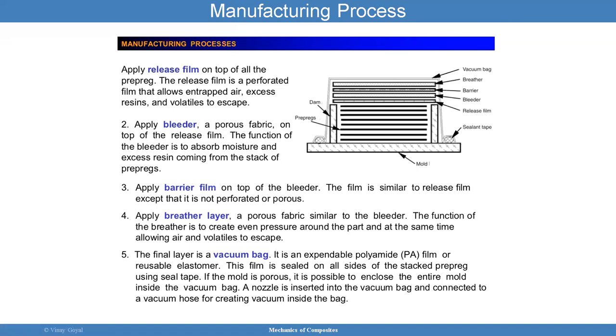We apply bleeder, which is a porous fabric, on top of the release film. And that lets you absorb the moisture and excess resin. Covered that already. Apply a barrier film on top of the bleeder. The film is similar to a release film, except that it is not perforated or porous. And then we apply a breather layer. And the breather layer typically allows you to apply even pressure, like I said before, around the part, and at the same time allows air and volatiles to escape.